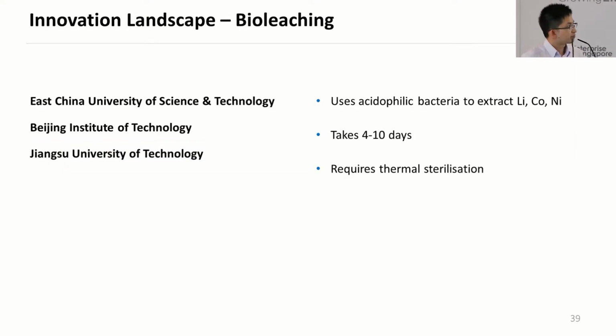The next one is bioleaching. Bioleaching involves the use of acidophilic bacteria. These are bacteria that thrive under highly acidic conditions to selectively extract lithium, cobalt, as well as nickel. The process takes 4 to 10 days. It's a rather lengthy process to achieve considerable recovery rates. The bacterial method also requires thermal sterilization upstream because bacteria are rather sensitive to contaminants. Not forgetting that lithium-ion batteries are hazardous waste which may contain a lot of contaminants that inhibit bacterial growth.